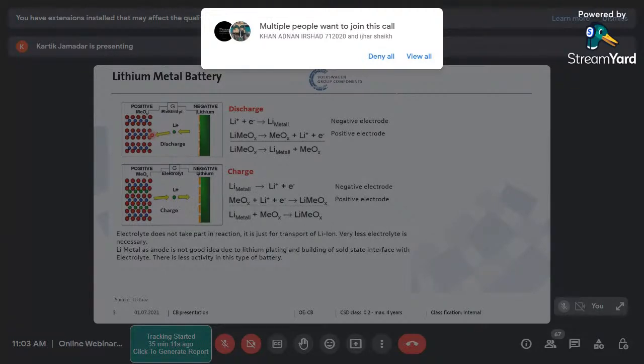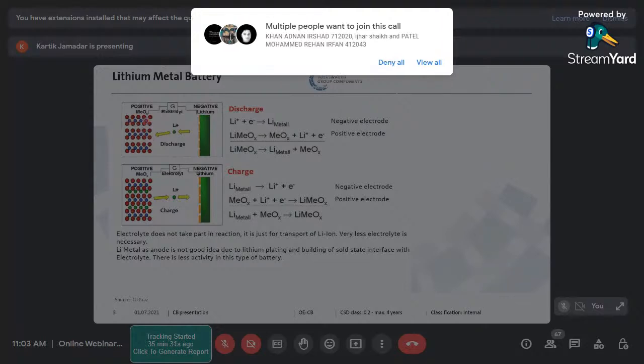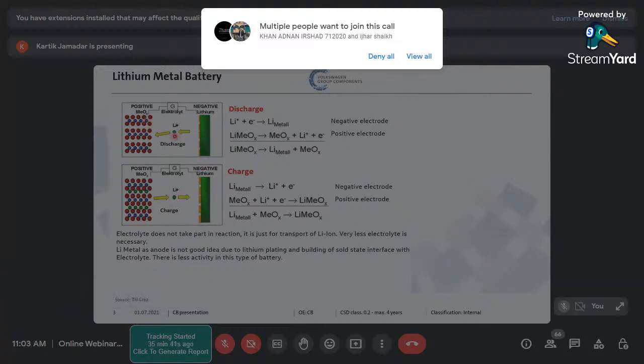I will not go into the detail at present. What is that metal oxide? So then we found a good battery, one obviously with a negative lithium as an anode, nothing better than that. That was a lithium metal foil. And on the positive side, we have these transition metals, changing the oxidation number, having the oxygen. The oxygen was creating the primary voltage, but the metal oxide was allowing the intercalation of the lithium, and the lithium was basically occupying the space. So this was happening during the basically discharge state. Same thing was happening during the charge state.